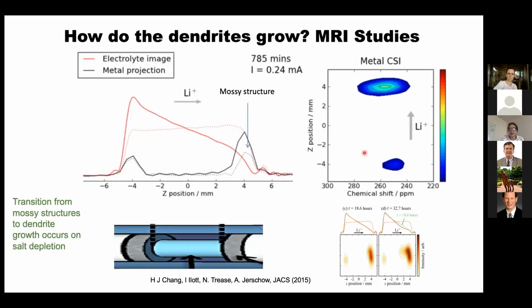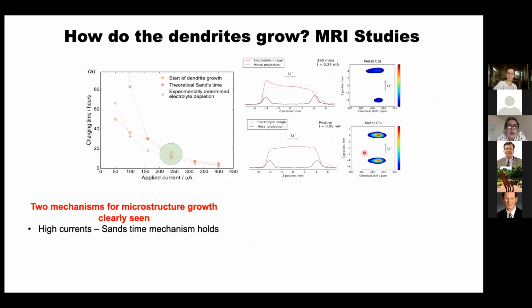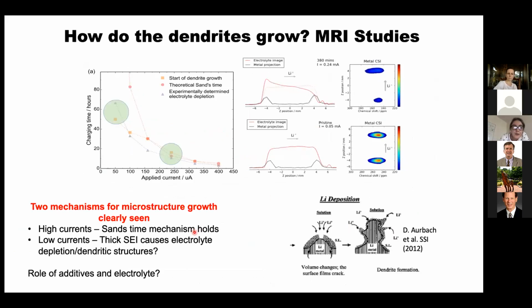So we can go back now, and we can go into the sort of classical studies of metal deposition and try and work out why and how this happens. And there's a study by Chazalviel and others who looked at this in the context of the so-called Sand's time. And the Sand's time is when that concentration of the anions drops to 0, and you get this sort of space charge mechanism. And we can look at the experimentally determined electrolyte depletion, and the start of the dendrite growth, and everything works out well, and our NMR tracks it.